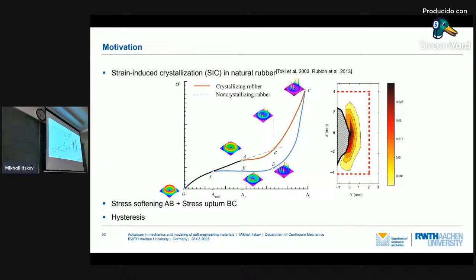Why is this crystallization so important? Because if you look at the stretch diagram of crystallizing rubber, we see that at the beginning we have small softening, but then very strong stiffening. Another important thing is that these crystals have a nice property: they can retard or even stop propagation of cracks in rubber. And this is very important for heavy load applications, for example, truck tires and so on. However, this